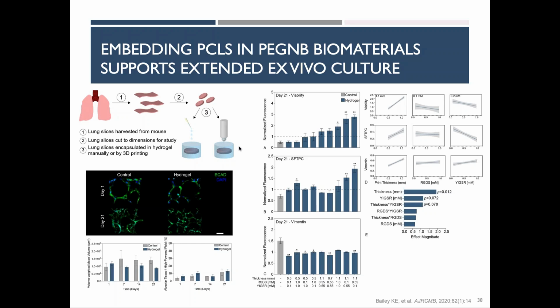So our laboratory has embedded these in a PEG norbornene-based biomaterial. So our precision cut lung slice is inside the biomaterial. This is an image of a slice through the middle of this. So E-cadherin labels the epithelial cells and then DAPI to show you the nuclei. And basically we used a design of experiments approach to optimize viability, surfactant protein C production, so functionality of the AT2 cells, and then to decrease vimentin, or to reduce the number of fibroblasts that are proliferating inside these materials. And we landed on a material that contains specific amounts of a specific thickness and specific amounts of RGD and YIGSR. And this has helped us to extend ex vivo culture of our precision cut lung slices from 7 days up to 21.